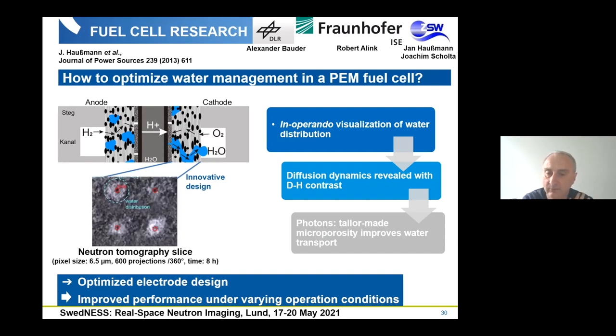For this, we performed neutron tomography imaging in order to observe where the water is during the operation of the fuel cell. And for this, we needed quite high resolution because the diameter of the hole was about 80 micrometers. The high resolution tomography, which we performed, has shown us that the water is not in the hole, but around the hole, which was not expected because the material used for this porous media was hydrophobic. And we didn't expect that the water would accumulate in the material itself. So this result was quite disturbing.